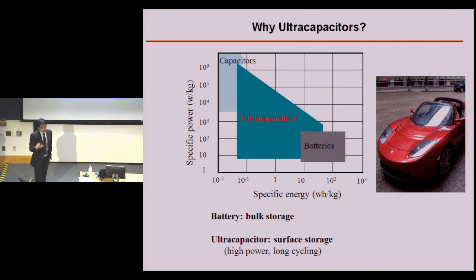So why do people want to use supercapacitors? You can see from this plot a comparison between specific power and specific energy density for battery and supercapacitor. Because a battery is using the whole bulk material to store charge, that's the reason why a battery has much higher energy density, but meanwhile has much lower power density. For a supercapacitor, it's using a surface to store charge. Everything can happen very fast. So that's the reason you get very high power density, but you have a limited surface area. So that's the reason the energy density is much lower than a battery.